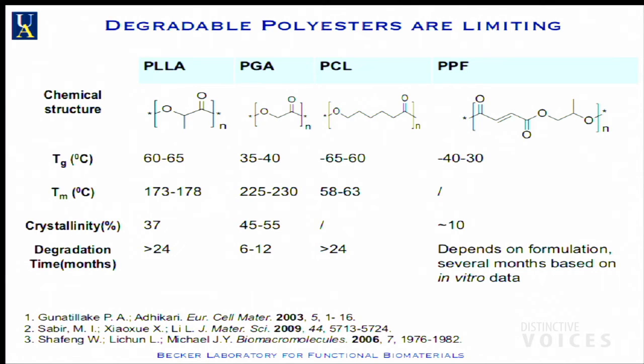Because the shelf life's not very good, and the printing processes aren't very good, so you've really got to control that. The glass transition properties, the point at which they soften, is pretty high. The bigger problem here is you get asymmetric degradation due to crystallinity.